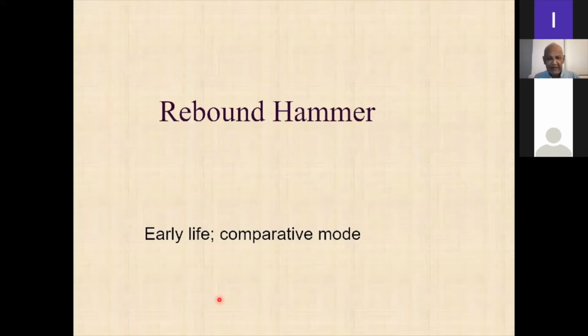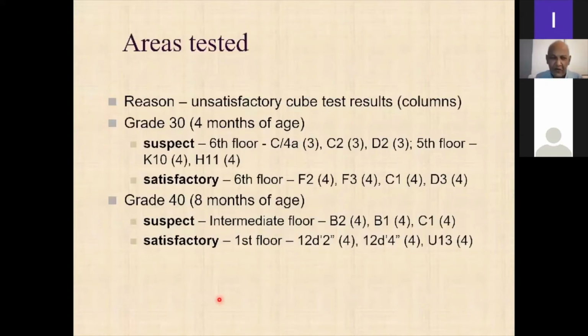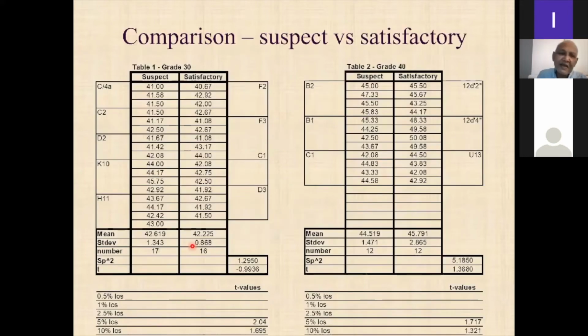In other words, comparing satisfactory and suspect concrete. So you had grade 30 concrete at 4 months of age, grade 40 concrete at 8 months of age, which is not very good because after 6 months there sometimes is too much carbonation. Anyway, what we want to compare is suspect versus satisfactory. For grade 30 there was suspect and satisfactory, and grade 40 also. These were in different parts of the structure.